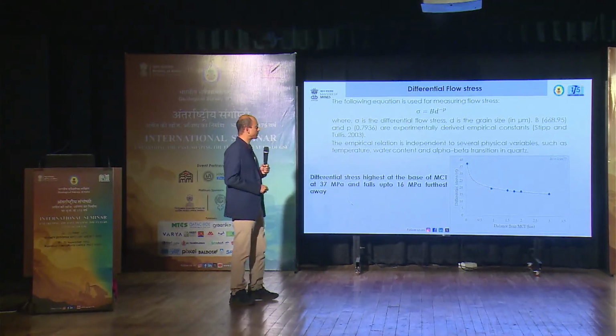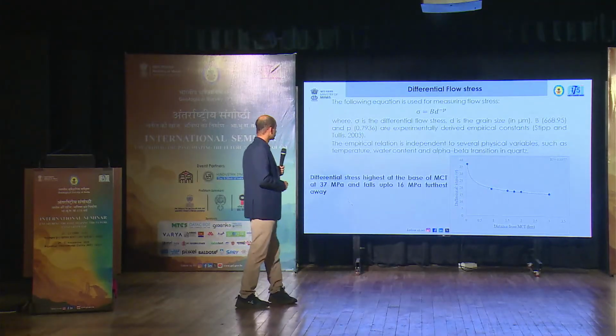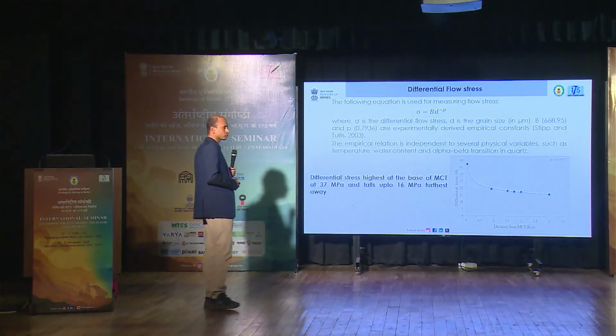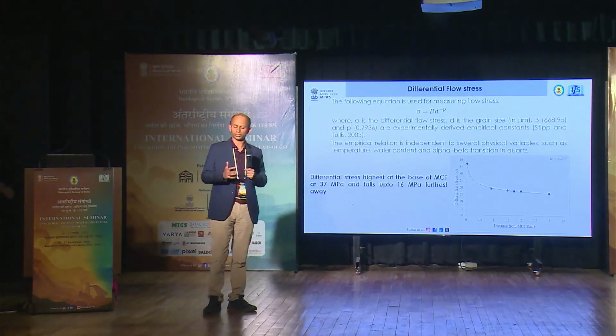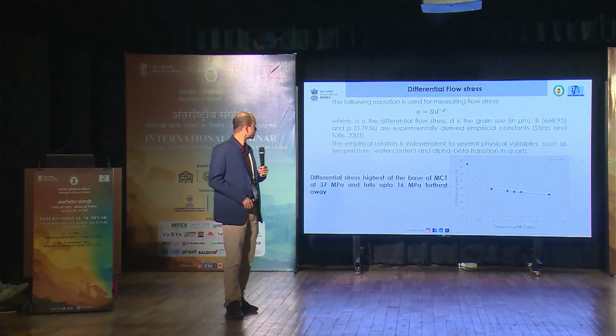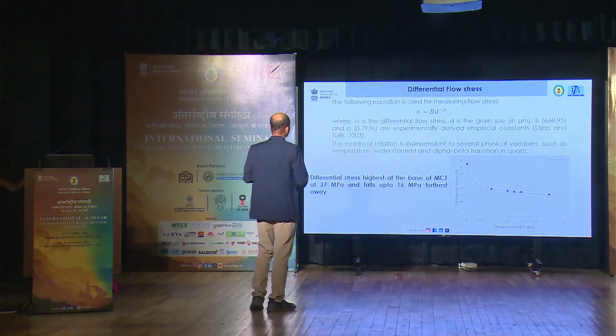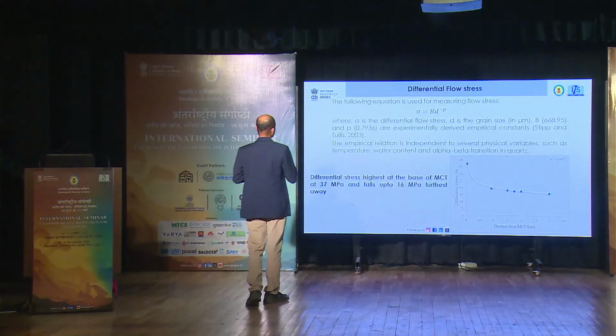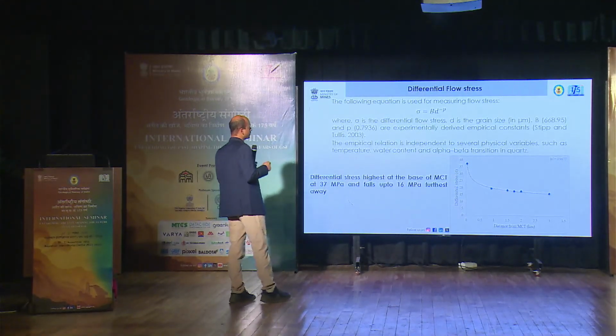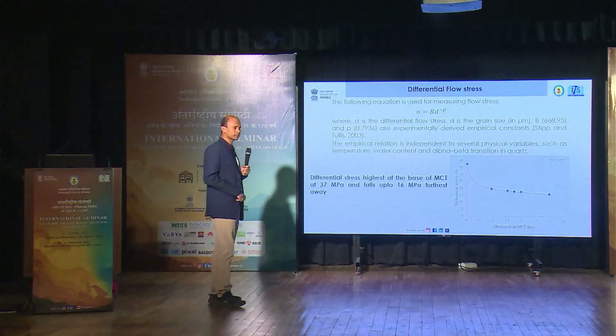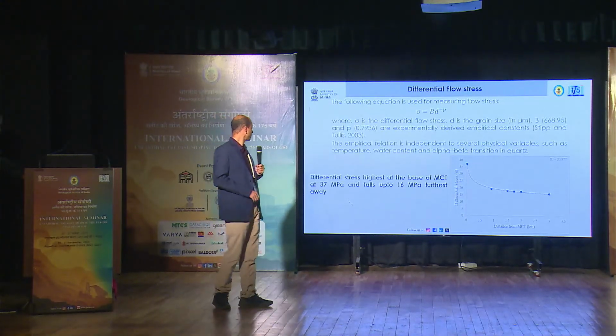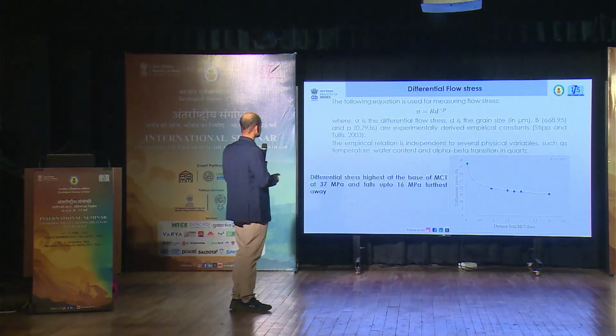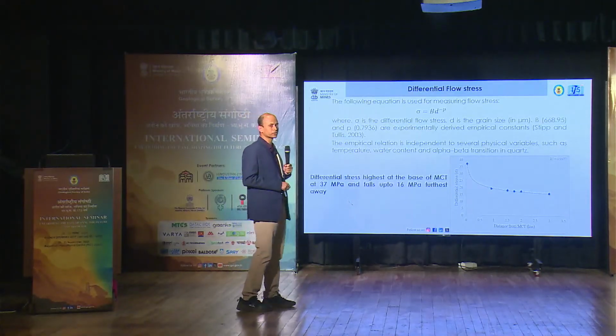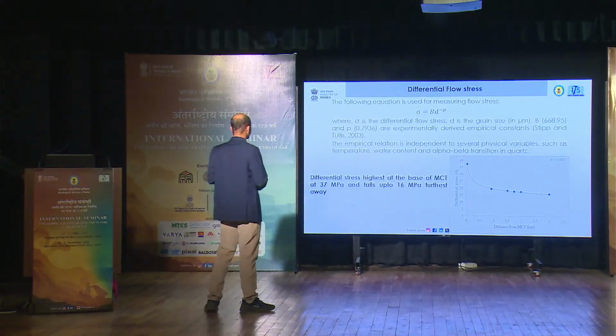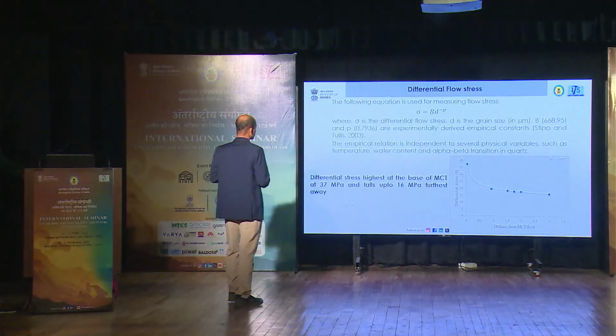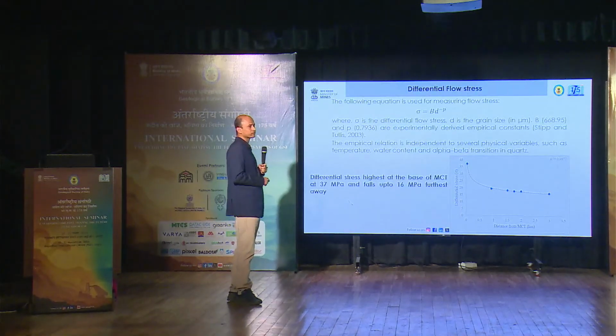Next. Then we have calculated the differential flow stress. This equation we have taken from Stipp and Tullis, 2003. They arrived at this equation through experimental studies in a Griggs apparatus. So sigma equals B times d to the power minus p, where sigma is the differential flow stress, d is the grain size, and B and p are experimentally derived empirical constants. What we observed was that the differential stress is highest at the base of the MCT. It is 37 megapascal, and it falls to 16 megapascal furthest away from the base of the MCT.